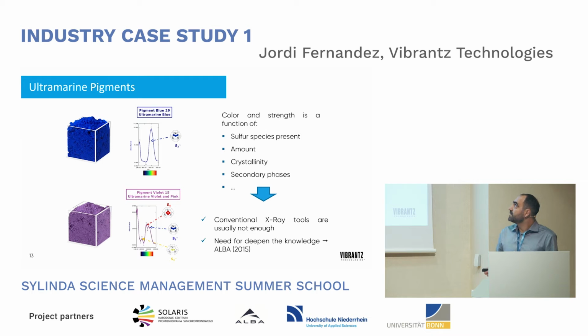So the color strength of this pigment is a function of the presence of the different sulfur species, the amount of these species, the crystallinity of the sodalite structure type, and then the presence or not of secondary phases. In this case, with conventional X-ray tools, the characterization, especially of the sulfur species, is not enough. And this is why we contacted ALBA in 2015 to start to deepen the knowledge on the ultramarines, trying to correlate the chemistry and the structural details with the quality of the final pigment that we are producing and selling.